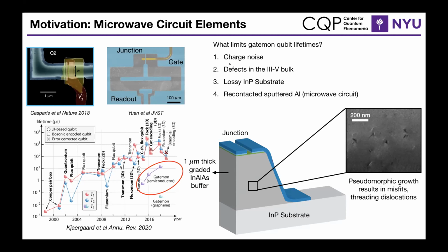But there are some things that we can do, and these come mainly in the materials quality. So number 2 here is defects in the III-V bulk. In the indium arsenide layer, we usually grow this on an indium phosphide substrate. But to do this, you have to grade the composition from that which is lattice matched to indium phosphide to one which is lattice matched or near lattice matched to indium arsenide. And we do this using a 1 micron thick graded InAlAs buffer layer. But in grading the composition, we actually introduce a lot of defects in the bulk in the form of misfit and threading dislocations. And these can be bad for microwave. These can be channels for absorption, which are not good for making resonators.